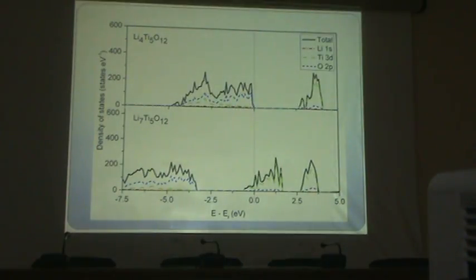He does some band calculations as well, and you see Li4 is insulating in nature, but Li7 is a little bit electronic in nature. So the electronic conductivity improves once you start putting in lithium. The idea was to develop this, then go for standard doping, picking up some standard molecule or material. People have done it, I think. But anyway, it was an exercise for us to learn as well, to see what doping does to the electronic structure. You can do this kind of calculation easily, he says.